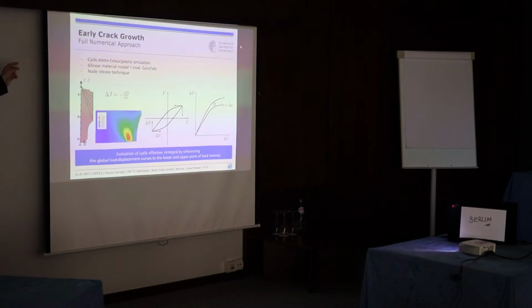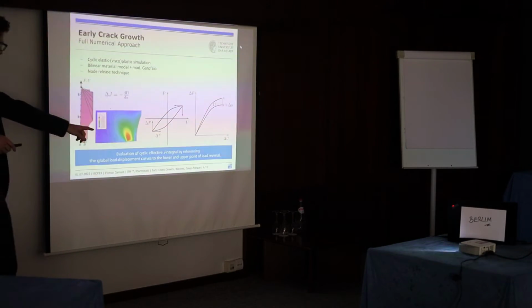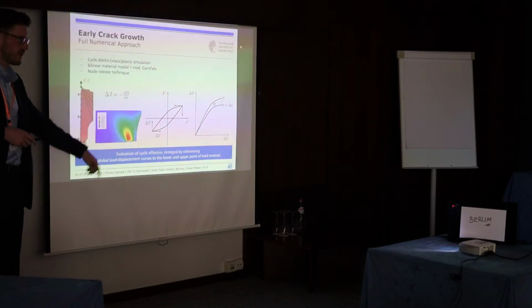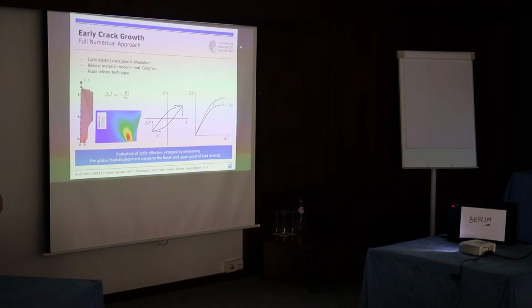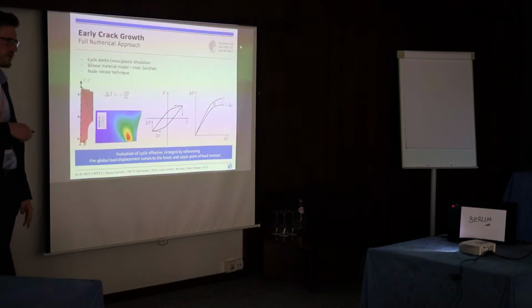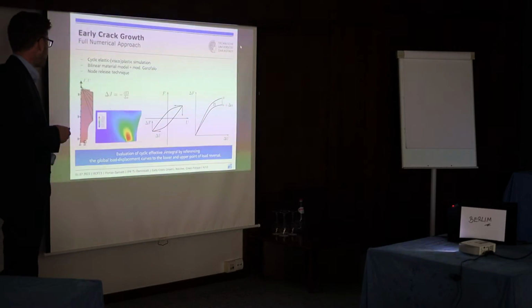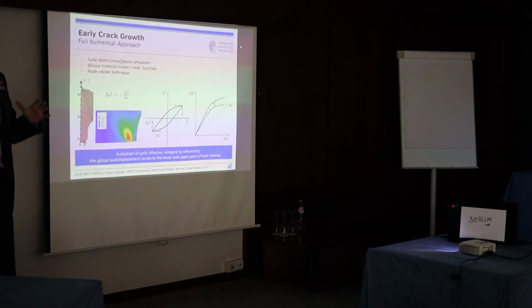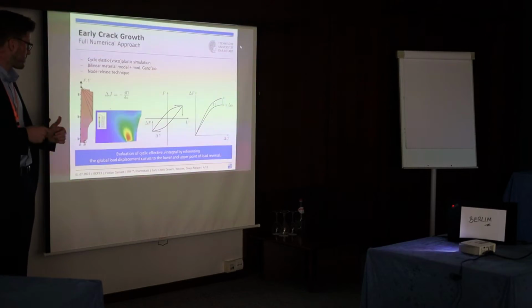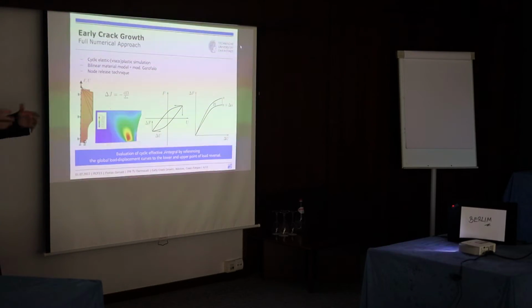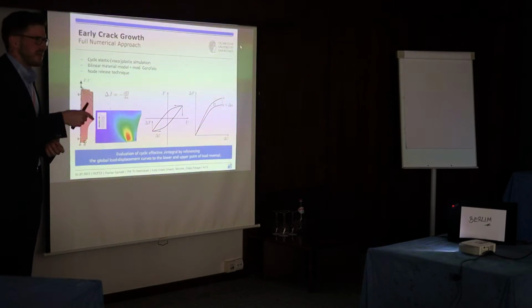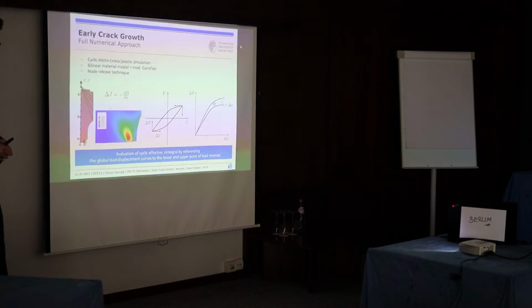Our computational approach is based on a cyclic elastic viscoplastic simulation. So we modeled this part here of the round bar specimen with notch. And we apply a bilinear material model for the elastic plastic part and the modified Garofalo creep equation to consider the creep behavior. And then we use one mesh from the beginning until the end of our simulation to keep all the information about plasticity and viscoplasticity. And we release nodes to let the crack grow.